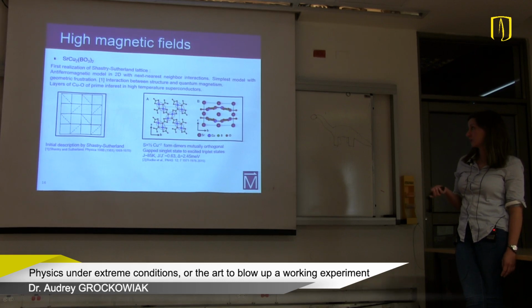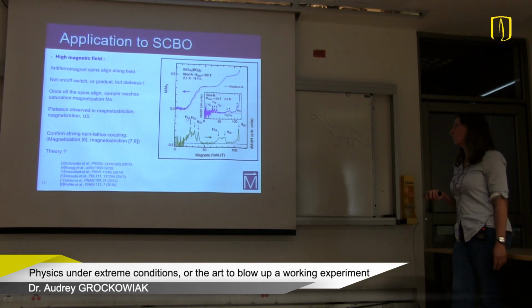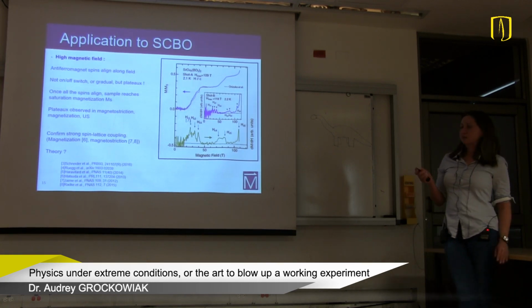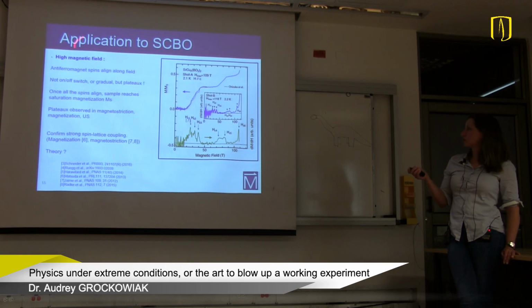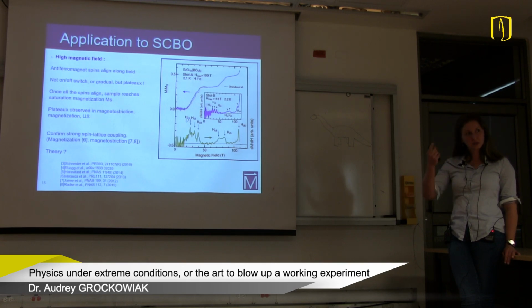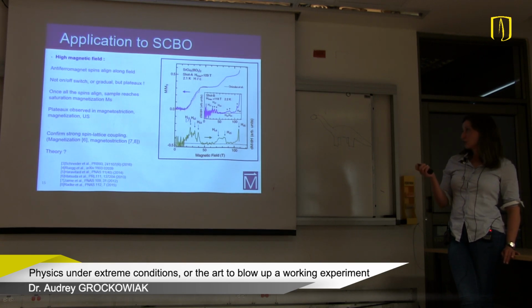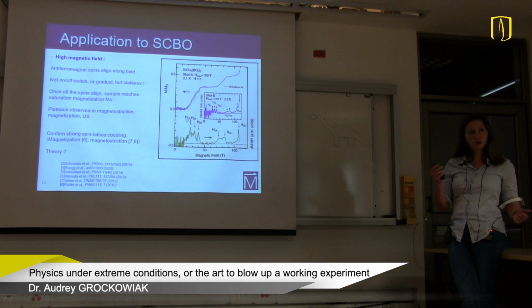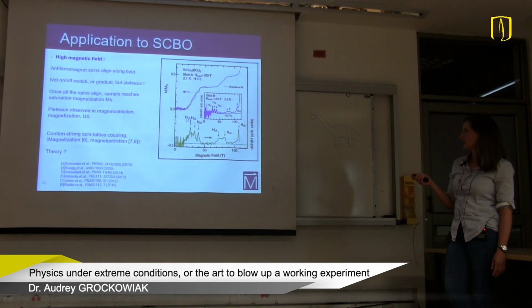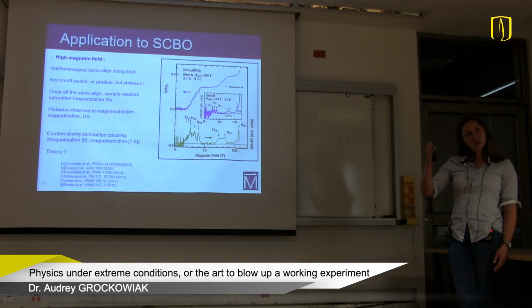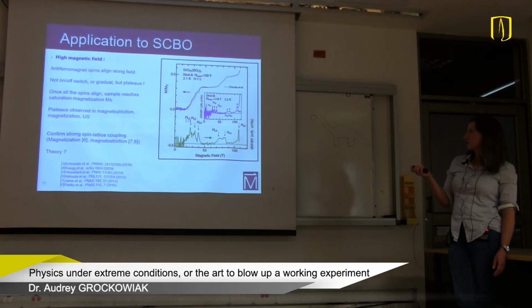And it's fascinating because Shastry and Sutherland did not really predict what happened then. So when we apply a high magnetic field, you basically go from an antiferromagnet to a ferromagnet because you align all of the spins along the field direction. So when all of the spins are aligned, you get to a ferromagnetic state where you have reached the full magnetization saturation, but it does not appear gradually or on-off, but actually appears as magnetization plateaus, so fractional amounts of the full magnetization saturation.